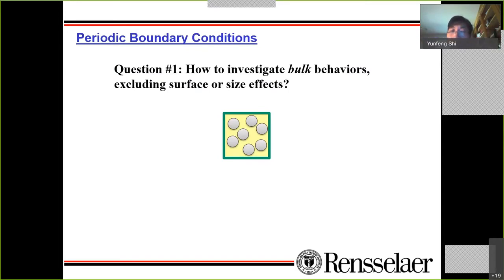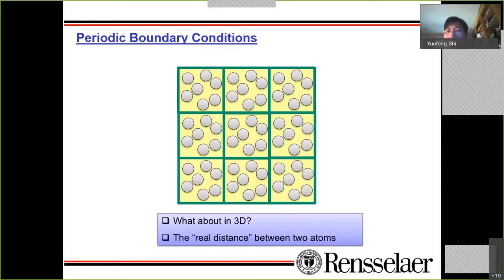So we have to answer the question: how can you simulate bulk behavior when you have such a small system? If the system is so small, a lot of it is exposed to surface, and we know that surface is different from the bulk. We have to solve this problem, and the solution is called periodic boundary condition. What does that mean? It imposes a constraint on the system. In this case we have 7 atoms in the system, right? Although you have only 7 atoms, we automatically consider that the system is duplicated in all